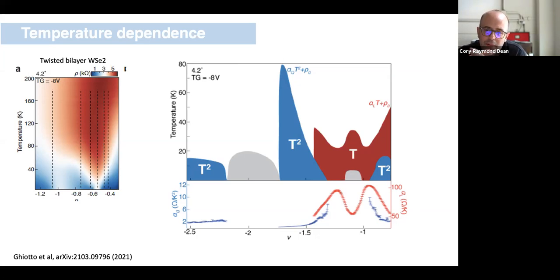Historically, a strange metal is defined as having a linear T dependence from the lowest measurable temperature range to the highest measurable temperature range that you could access. Here, our T-linear regime cuts off at some high temperature value where we see the saturation dependence. And partly why that would not be unexpected in the system is that we have quite a finite bandwidth in energy, beyond which if we heat the system too much, we start to access the higher energy band.